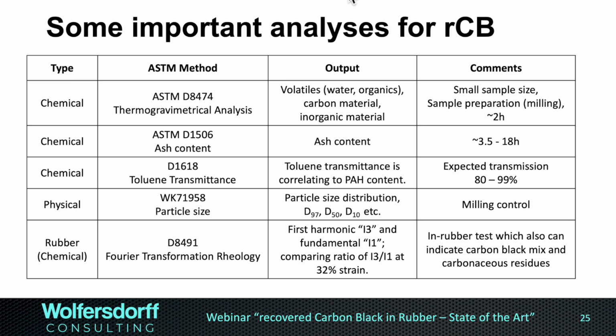because if we use the ash content method, it is anything between 4 to 18 hours, so that's like an overnight test, depending on the sample preparation, which takes much more time. And then, of course, if you want to use that as a process control test, you're like 18 hours behind of your process, which is not so good.